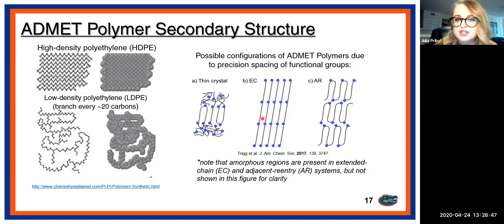In an extended chain conformation, or EC, as it will be denoted later on in the presentation, the functional groups are actually incorporated into the polyethylene crystal. So they have this sort of extended chain structure. And then finally, adjacent reentry is this example here, where at every instance of the functional group, the polyethylene backbone undergoes a turn. So you end up with these crystallized polyethylene segments, and then the functionality ends up facing each other into this sort of layered structure. One thing to note: never trust what a cartoon shows you, because this cartoon is incomplete. In these two cases, the amorphous regions also exist in these type of polymer systems, but they're just not shown in this cartoon for clarity.